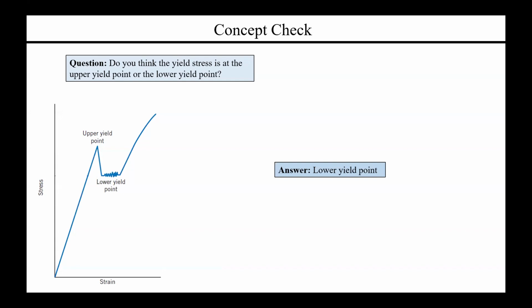And there is no requirement that that transition point happen at the maximum stress that can be met prior to plastic deformation. This is an interesting caveat, in that you can have scenarios where you can sustain a fairly large stress, but then something happens in the structure of the material and you see a drastic drop off in the stress that can be handled. And then it's only after that drop off that you actually see permanent damage to the material.